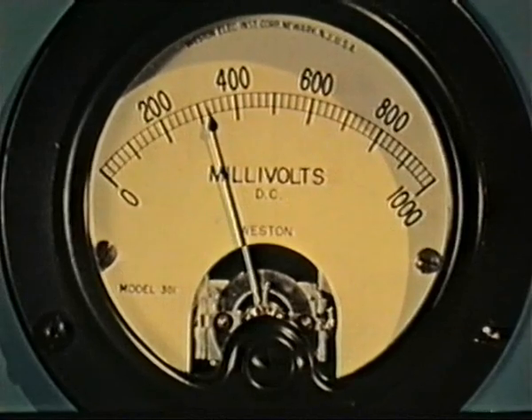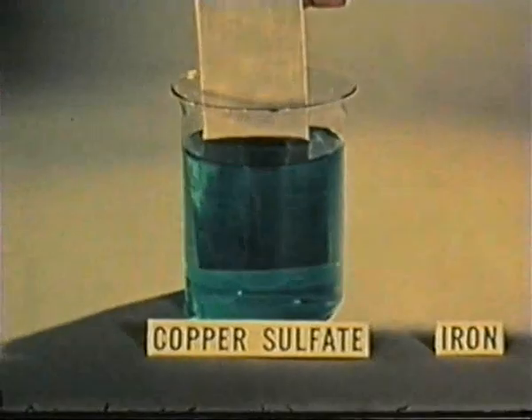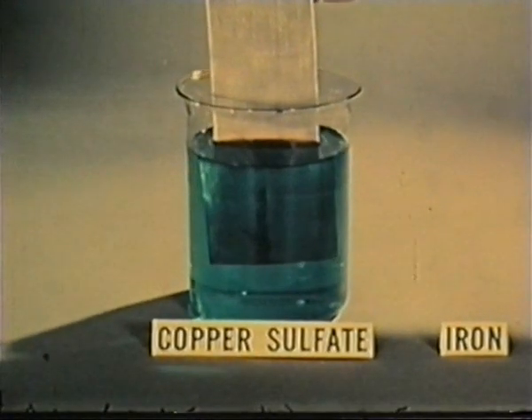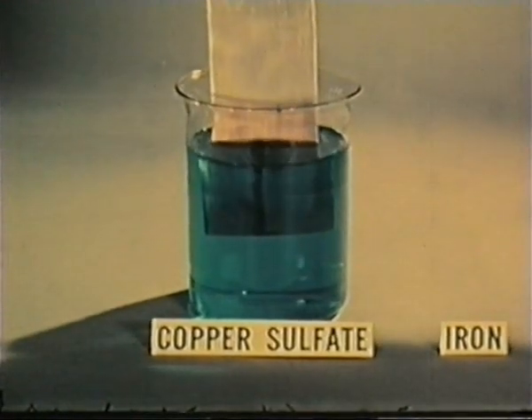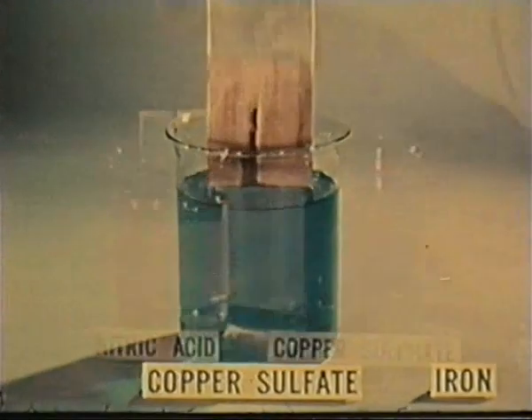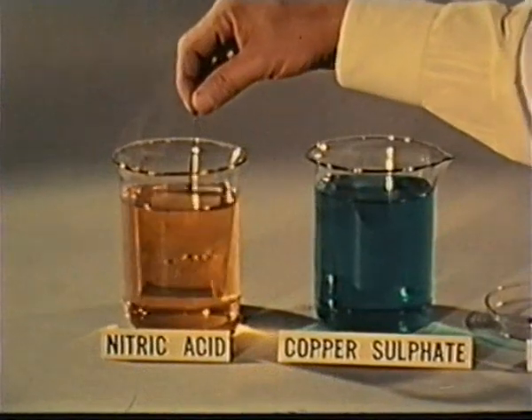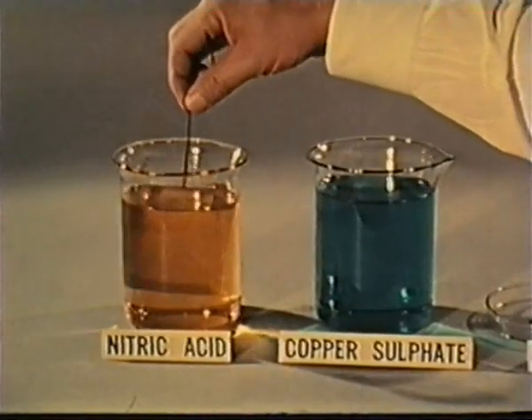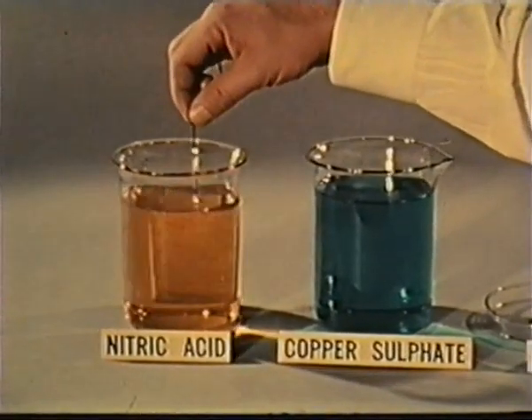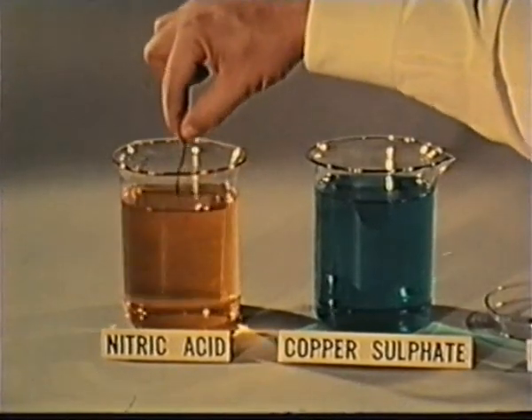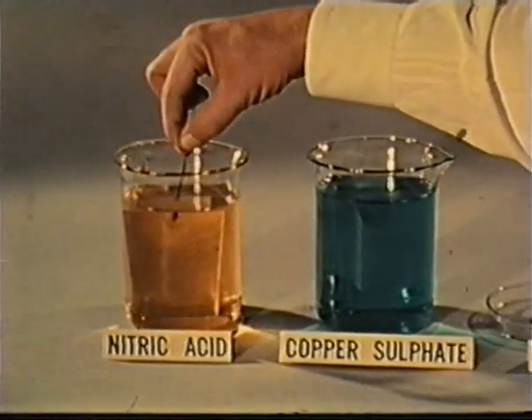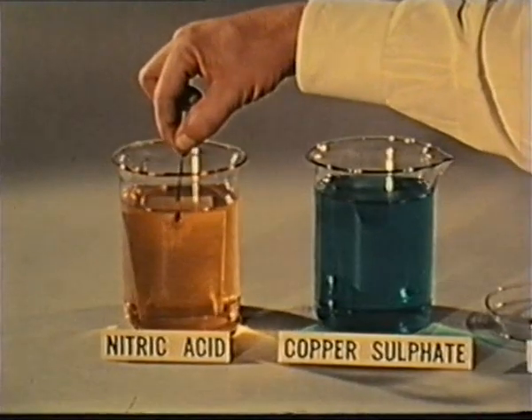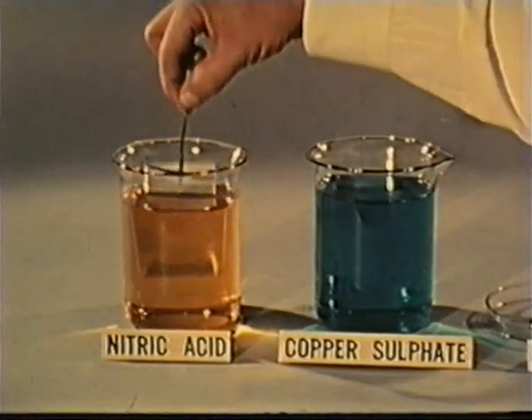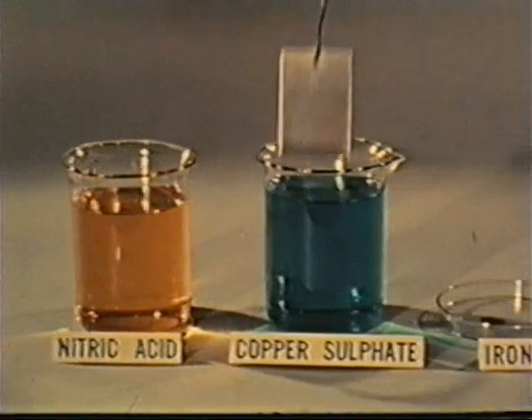For illustration, active iron when dipped in a copper sulfate solution will cause plating out of the copper. But now, if we make a piece of iron passive by immersing it in nitric acid, a protective film formed by the nitric acid prevents corrosive action. If we dip this passivated iron into copper sulfate, no plating out of copper occurs, but a light tap is sufficient to rupture the passive film. The iron becomes active again.